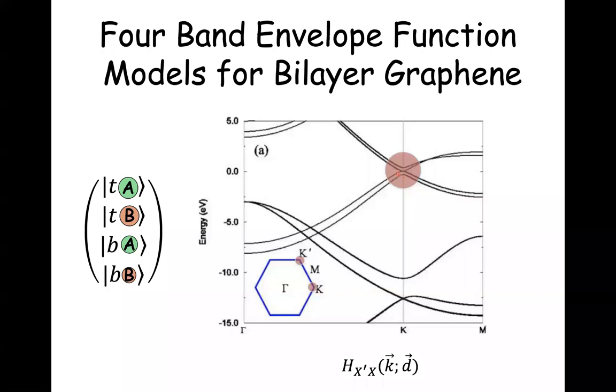And you can also see that there are 2 states that are especially low in energy. They actually touch here at what is 0 momentum if we measure it from the Brillouin zone corner. And there are 2 other states that are pushed away in energy. Because there are 2 layers and 2 sublattices in each layer, you would have expected 4 low energy states, but the Hamiltonian splits out 2 of them. And something very similar is going to happen when we have a twist angle.